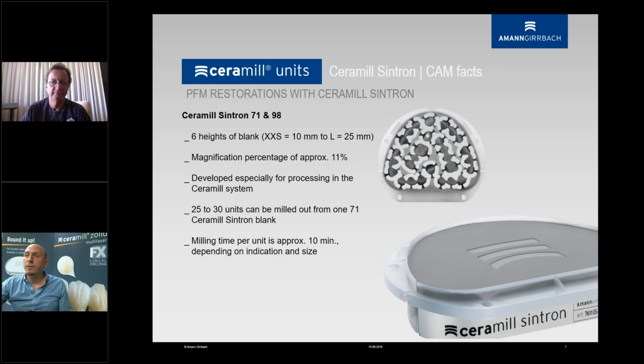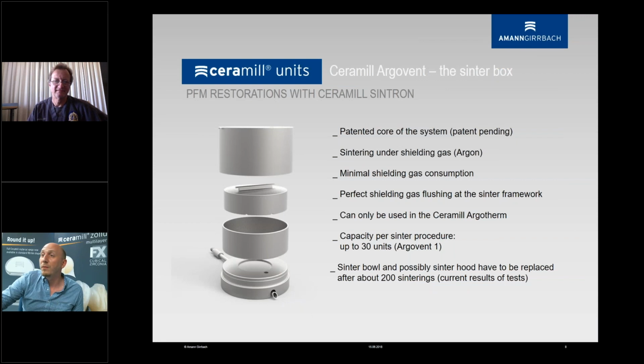It's developed specifically to be processed with the Ceramill system, but now others can also do that. I know in the beginning some of the Roland mills had some issues milling it, but meanwhile I think it had to do with the exposed rail, but Roland made some changes to it, and I think they have it officially listed meanwhile. We're looking at about 25 to 30 units out of a 71 blank, because it's usually a cutback, so it's a little smaller, right? Milling time is approximately 10 minutes. That's a very average number because it really depends on which kind of strategy you're picking. You have such a vast choice now: standard, fine, HD, margin standard, margin HD, undercut standard or HD. So that can go somewhere from 10 to maybe up to 25, who knows.